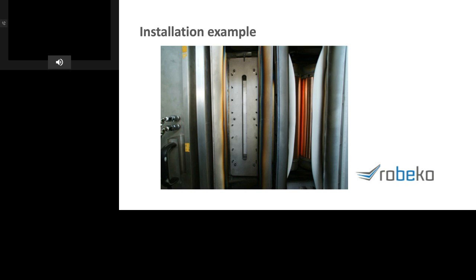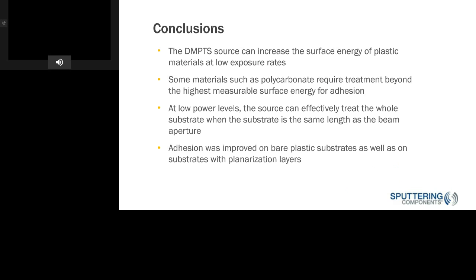So in conclusion, we showed the DMPTS source can increase the surface energy of plastic materials at low exposure rates. Some materials, such as polycarbonate, as we saw in that last graph, require treatment beyond the highest measurable surface energy for adhesion. And at low power levels, the source can effectively treat the whole substrate when the substrate is the same length as the beam aperture.